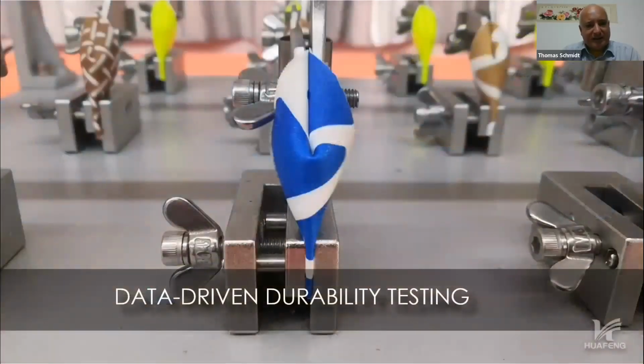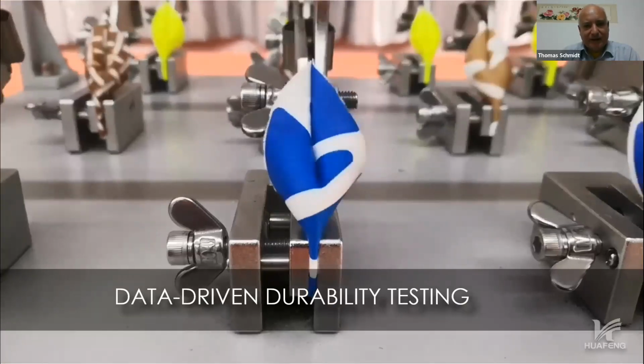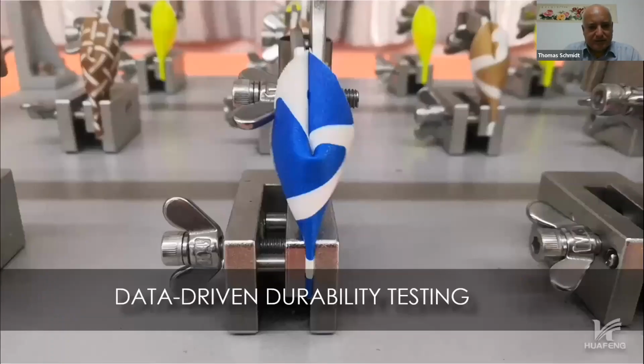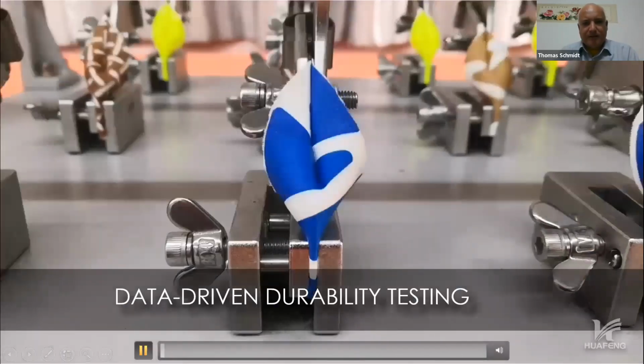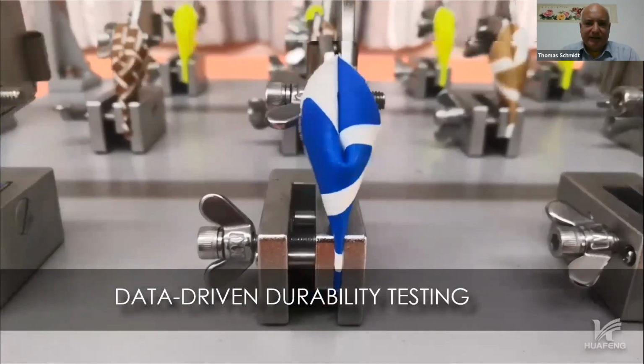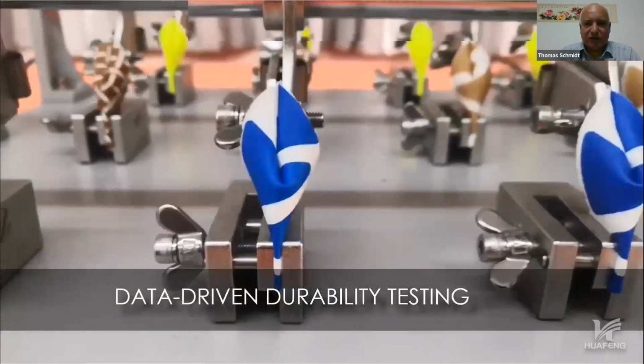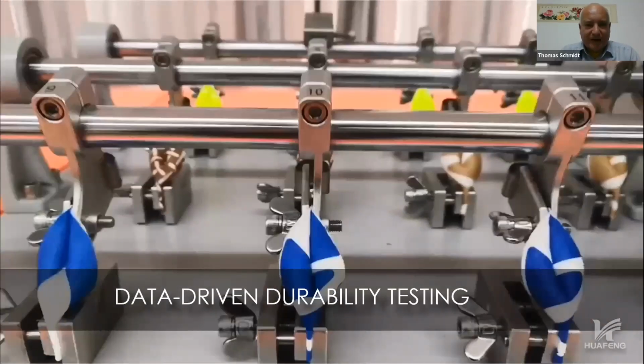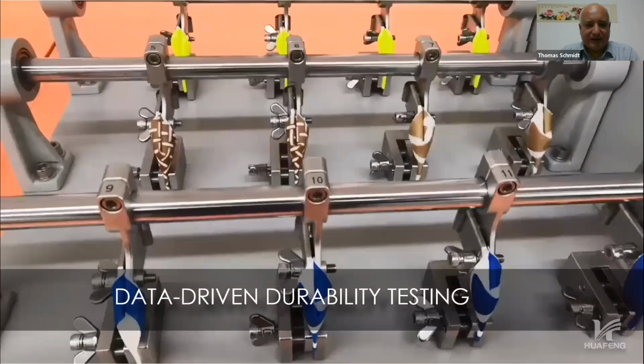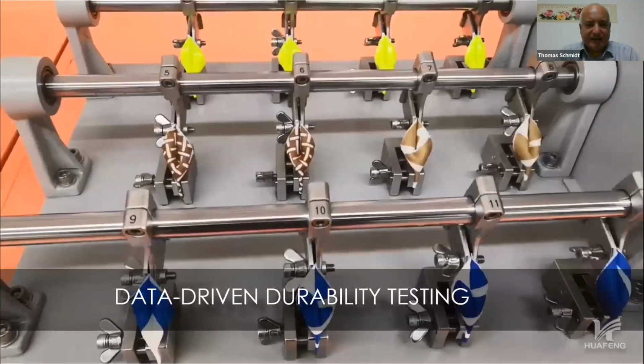We do a lot of data-driven durability testing in our lab, and this is the Bally flex method. There should be a little video here. The Bally flex testing, where you see we simulate the walking performance of a shoe, and we do that for at least 100,000 times, and then the coating is very carefully examined and checked if there are any cracks happening. So usually haptic performs very, very well, and even in cold temperatures, like Thomas Beek has shown you already, we can do Bally flex for up to 100,000 cycles.